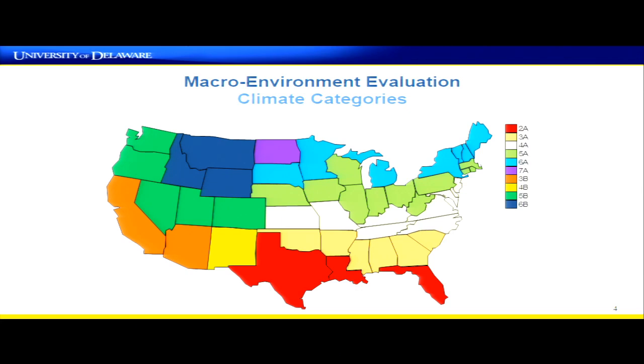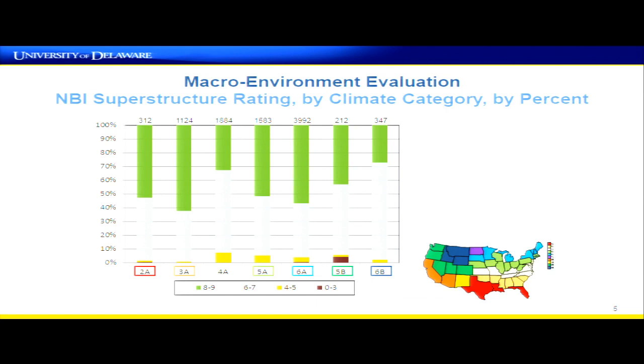So we look at the bridges within each of those climate categories and look at how they perform. And so what we see here is the NBI ratings of bridges in those climate categories and what the distribution of those NBI ratings are. So for example, what percentage of the bridges have a rating of 8 or 9 would be green, ratings of 6 or 7 are blue. We see, first of all, there's not that many that are low ratings. And we also see that there's no clear trend here. So as a function of macro environment, there's really not any clear trend that really emerges here.